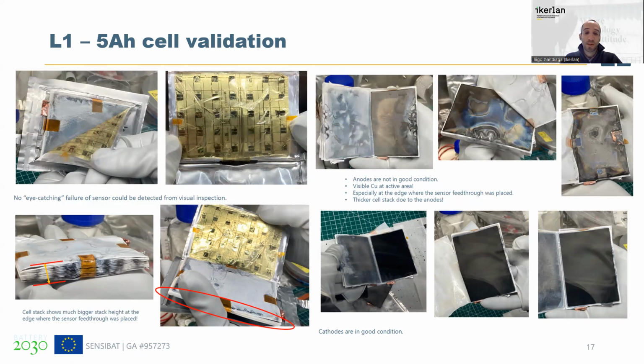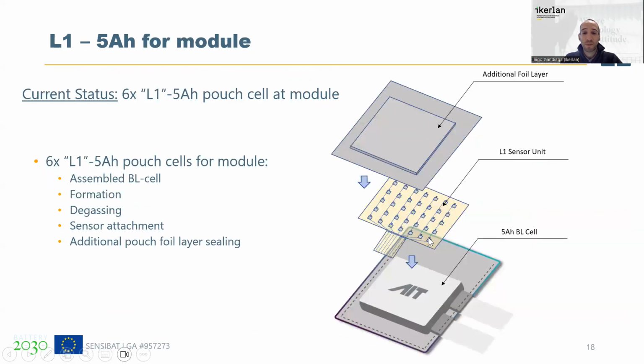So what we did, we used the same sensor, the same glue, everything the same, but instead of placing it in contact with electrolyte, we placed it on top of a baseline cell, which is a normal 5 ampere hour pouch cell. Then we placed the sensor, and we did like an additional pouch layer to the outside to have the sensor inside the cell with the vacuum and everything as if it was placed on the inside.